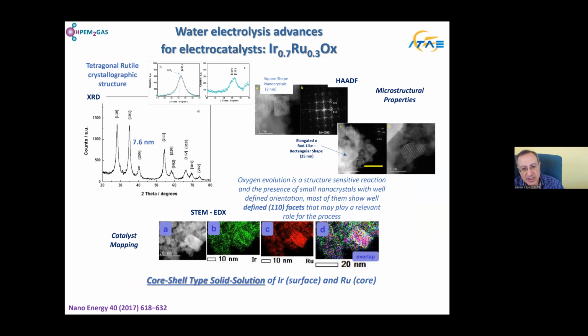Coming back to the materials, I'm showing you this to emphasize that the key advantages we achieve on materials reflect on much better, more efficient technology. I mentioned the crystallographic structure plays an important role, especially for the anode, for the oxygen evolution reaction, which is a rate determining step. We need small particle size but still crystalline.